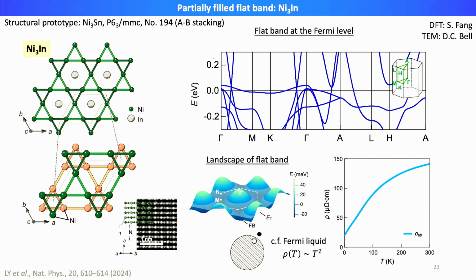We're looking at the electrical resistivity as a function of temperature, right? We're able to see this characteristic trace. Below about 100 Kelvin, you see approximately a temperature-linear resistivity.